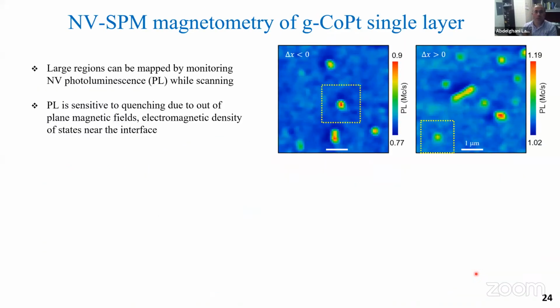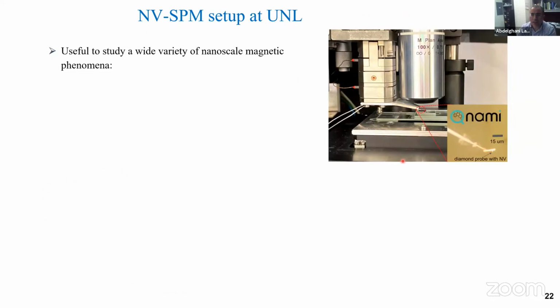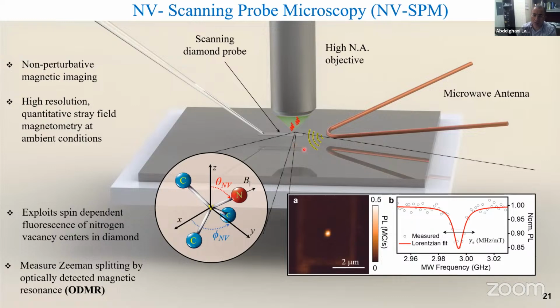So to go to the materials we are interested in, as I said, the idea here is you scan, and you bring the magnetic sample here. There are two ways to measure. Either you look just at the intensity of the fluorescence of these NV centers and do optical mapping, or you do quantitative measurements. You do the full ODMR for each pixel, and by looking at the shifts, whether to low or high frequencies, which depends on the orientation of the field, you can get a magnetic image.